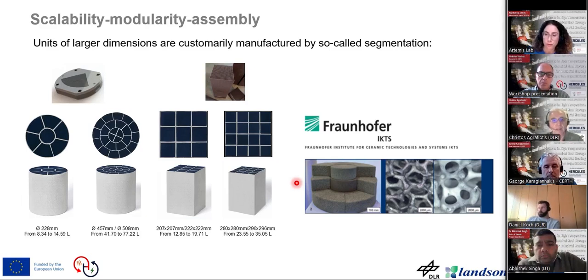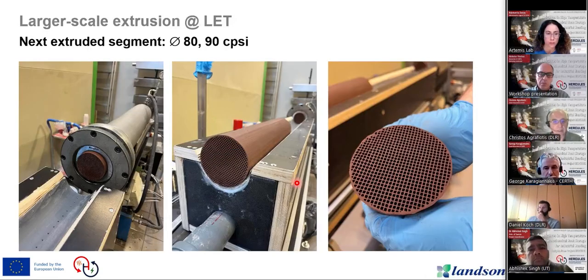One can assemble units of bigger dimensions along and across from smaller elemental pieces that are easier to manufacture in defect-free cases. And if we go to the next slide, we will see how our partner LANDSON has scaled up these extrusion techniques. Here we see a perovskite body extruded in an extruder of diameter of 80 millimeters, 8 centimeters. You can see that it's practically flawless by naked eye, a perfect honeycomb, and a large one.